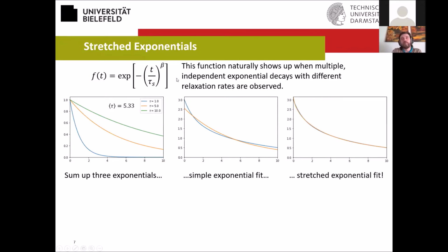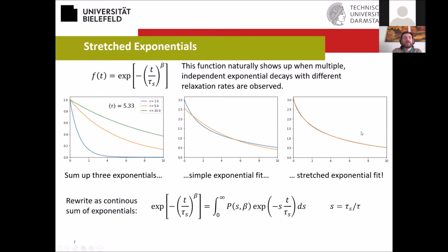Using instead this expression with a stretched exponential to fit the sum of these 3 exponentials gives you a very, very good agreement. And the reason for this is that there is a transformation that tells you that you can always rewrite an exponential as a stretched exponential as a continuous sum of exponentials. And from this, you get this mean relaxation rate. And from this fit, you can extract some parameters, beta and the stretched relaxation time. And when you now calculate the corresponding mean relaxation rate, this is 5.33 for this fit, which is very close to the exact solution that you would expect. So this is the beauty of the stretched exponentials, that they naturally include looking at an ensemble of multiple relaxation times.